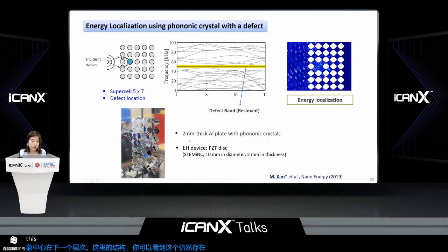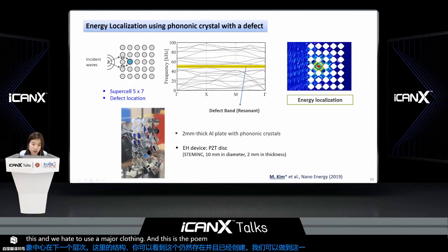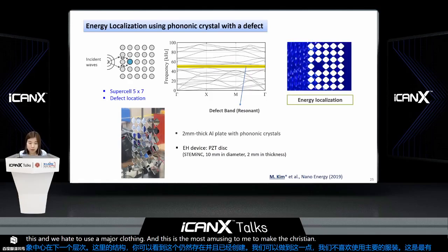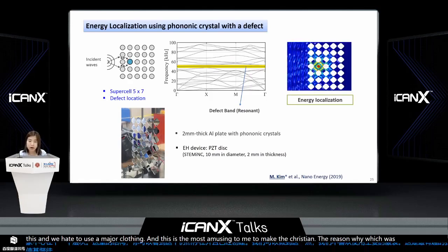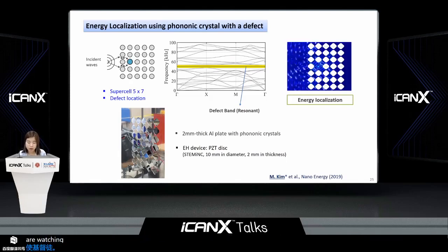So we can use this defect band. And we fabricate using laser cutting. And these are the octagonal holes, using a 2 millimeter thick aluminum plate to make the phononic crystals. The reason why we chose aluminum plate: a lot of people who are working on elastic wave research, wave-related research, normally use aluminum plate.